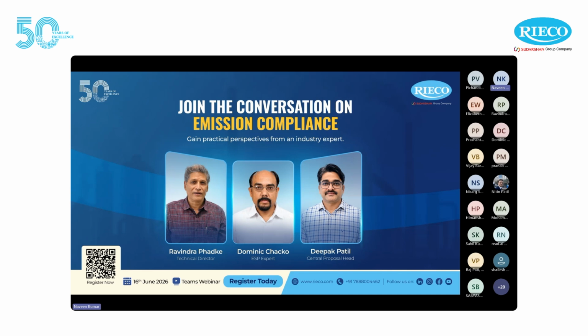The challenge in treating these off-gases is that the particulate matter has particle sizes that even go to submicrons. In many cases, it ranges from 5 to 10 microns. So, of course, the selection of the baghouse, keeping the air to cloth ratio right, is vital in this. Since these are tiny submicron particles, we have to carefully select the cleaning methods. Of course, it is the offline cleaning method, with the air to cloth ratio and the entries of the bag filter casing designed so that we can get rid of re-entrainment of the dust, since the micron sizes are very small.